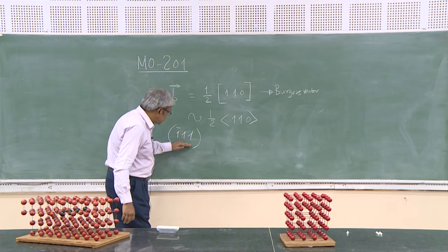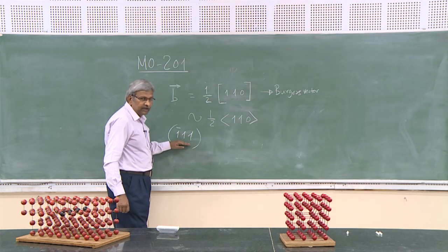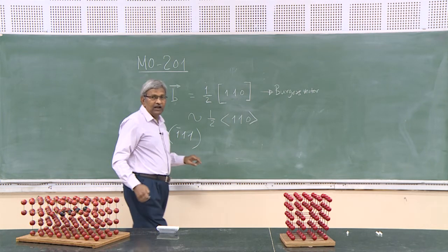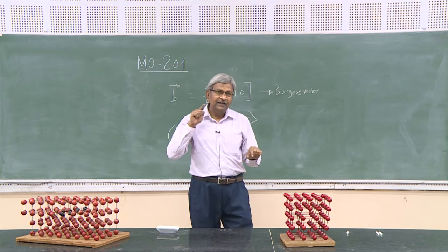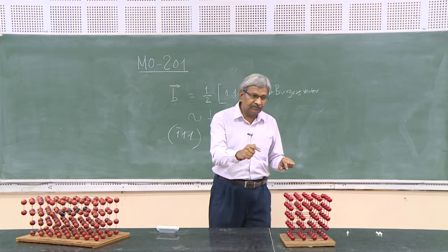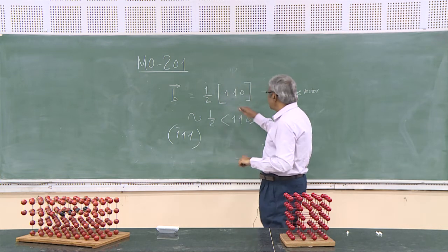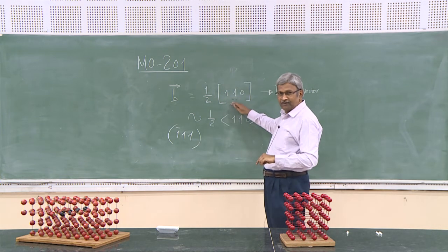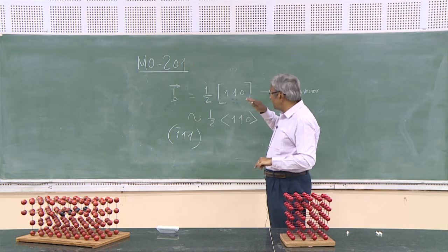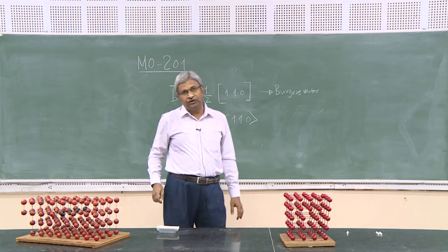Meaning thereby that all the triangular faces of the type 1 1 1 will have the sides of the equilateral triangle given by any of the permutations of 1 1 0 type, and all such 1 1 0 type can be decomposed into 2 1 1 type.